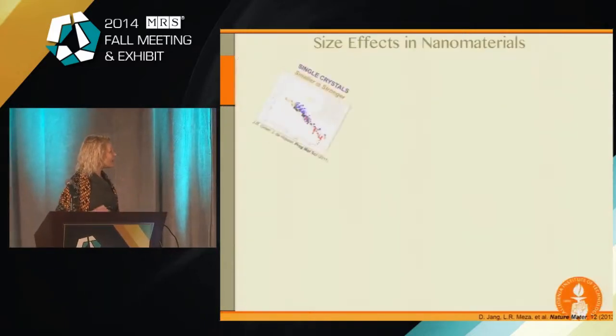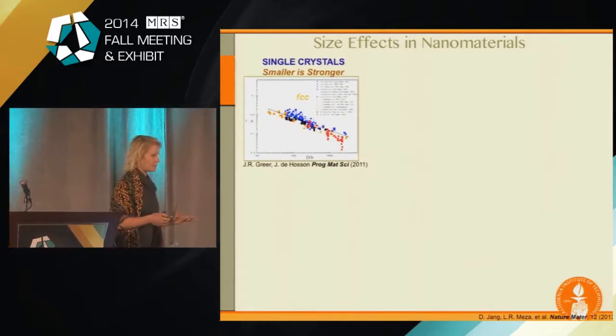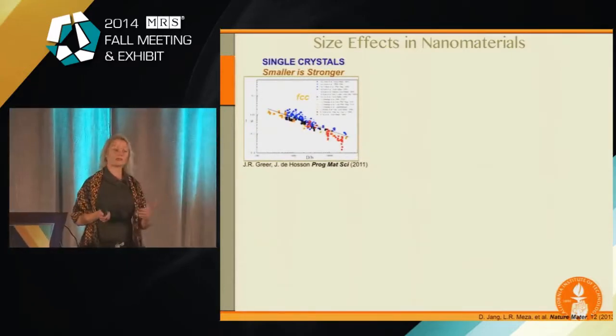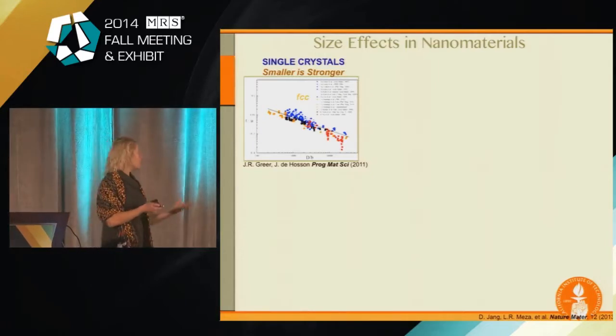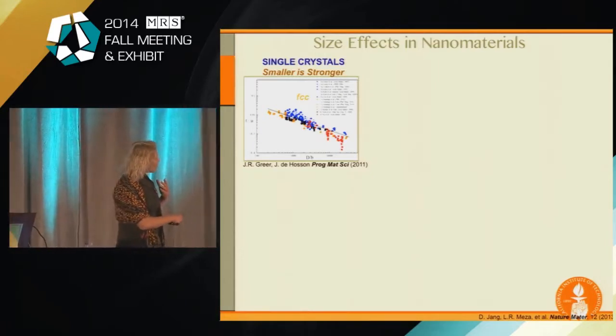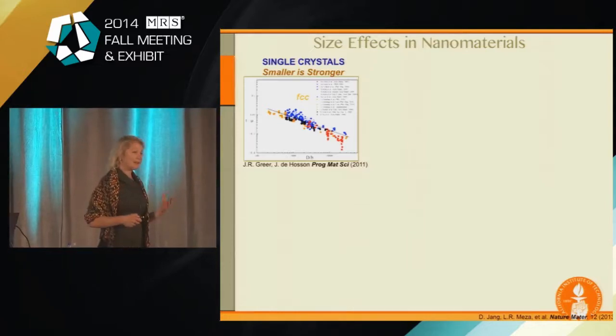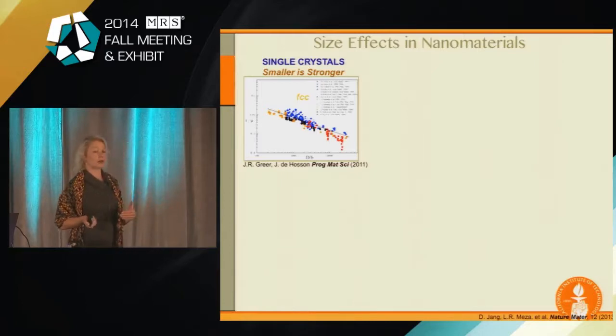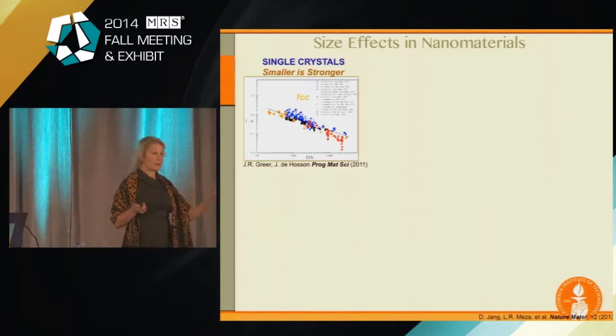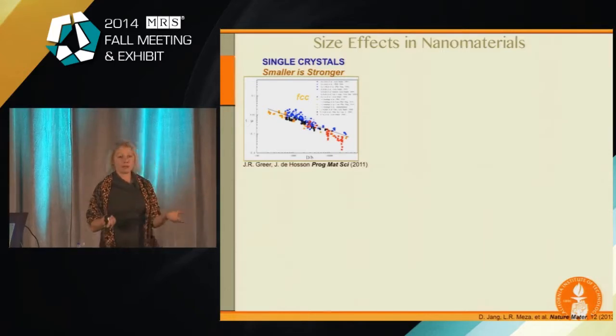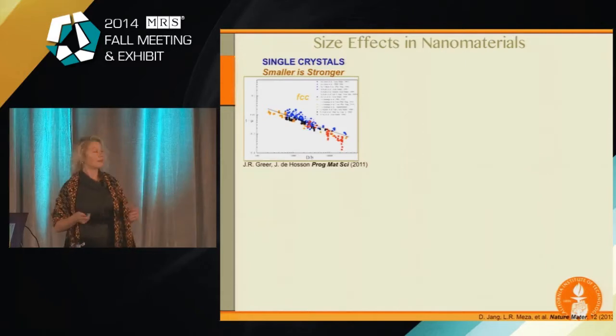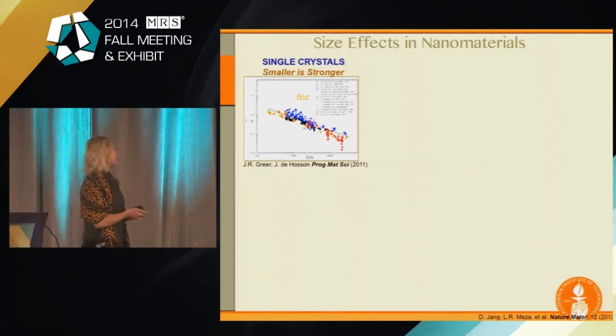So what I mean by this is that there is a so-called size effect in nanomaterials. If you take a common metal, gold, copper, nickel, in its very pristine form, you can plot its strength as a function of its size. And what you'll see very quickly, again, this is a log-log plot, is that there is this phenomenon that's called smaller is stronger. So for these metals, you take gold, it's very malleable, you reduce it to the size of about 200 nanometers, and it becomes as strong as steel. There are reasons for that, and I'm happy to talk about that as well, but that's not what this talk is about. So smaller is stronger. So what that tells us is that maybe we can tune the strength by size reduction.